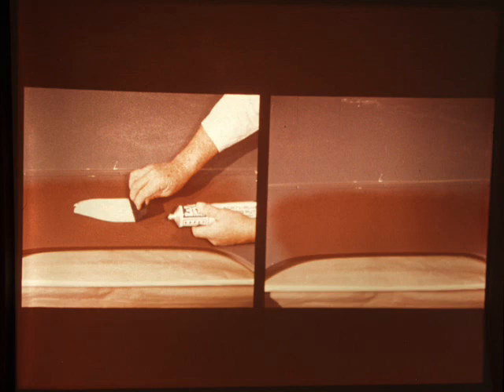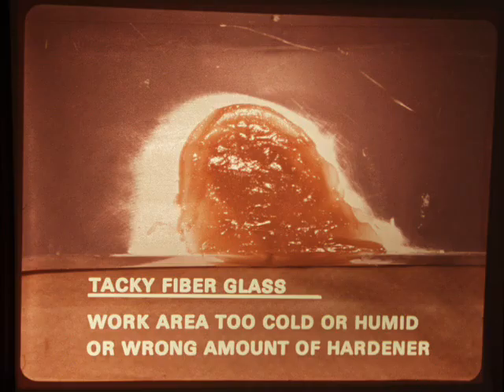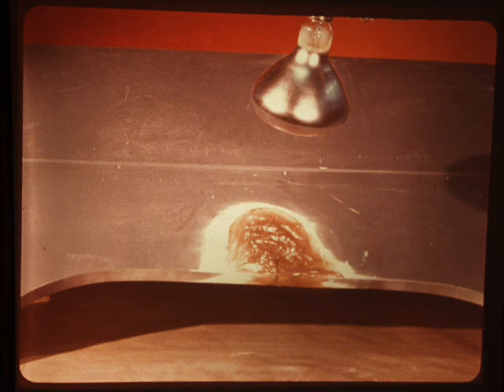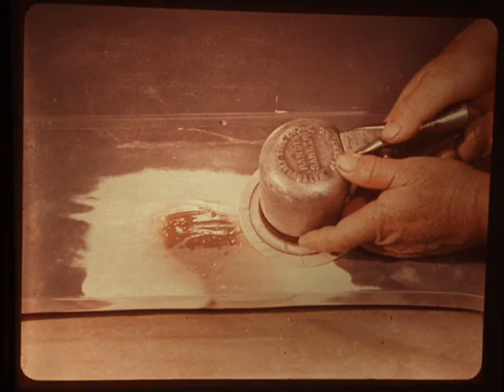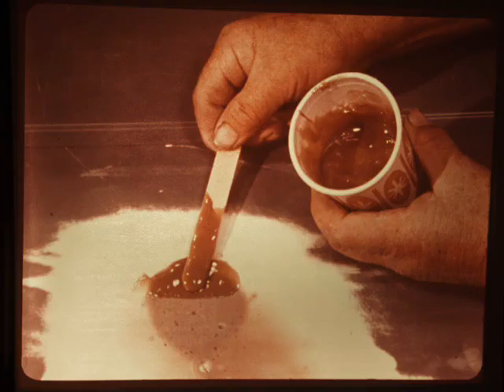If you encounter any problems in the procedures we described, the most likely one is that the fiberglass becomes tacky. As mentioned before, working in a too cool or humid area can cause the fiberglass to absorb moisture and become tacky. It can also become tacky if the amount of hardener used was not correct. The way to correct it is to first try to dry out the area with heat lamps. Then peel or scrape off the top surface or sand it off with a power sander. Next, reapply the layers of resin you need to